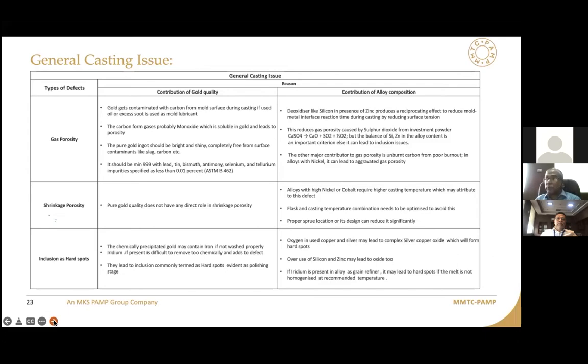Most of the time casting is an issue where you get lots of gas porosities, very micro porosities, which is very difficult, especially when you go for a 10x magnification. You find that there are so many that you can't repair them all. And the pieces move on between solders, lasers, and productivity goes down. Now, how does gold quality matter?